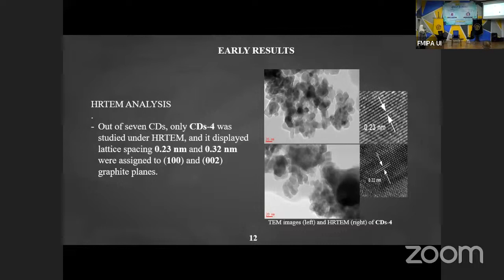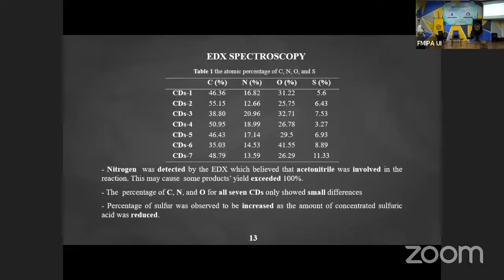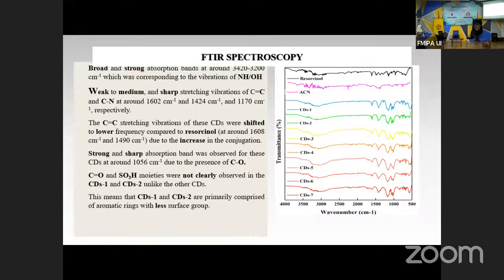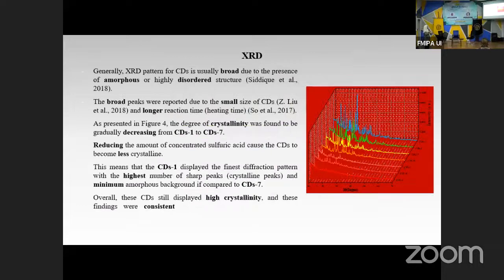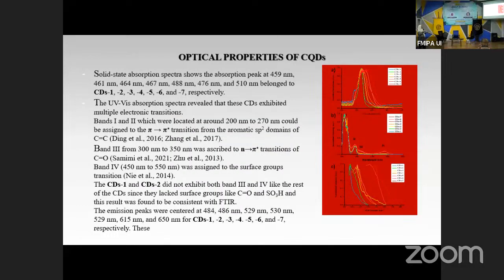Some of the HRTEM analysis, okay, out of 7 CDs that he managed to prepare, only CD 4 was studied under HRTEM, and it displays a lattice spacing of 0.23 and 0.32. And then he also did some EDX study, and he found out that nitrogen was detected by EDX, which we believe means that acetonitrile was involved in the reaction. And the percentages of carbon, nitrogen, and oxygen of all 7 CDs showed small differences. You can see from the table. And percentage of sulfur was also observed. He also did FTIR to see the functional groups present. And he also did some Raman spectroscopy, 1H-NMR, XRD, optical properties of CQD, etc.